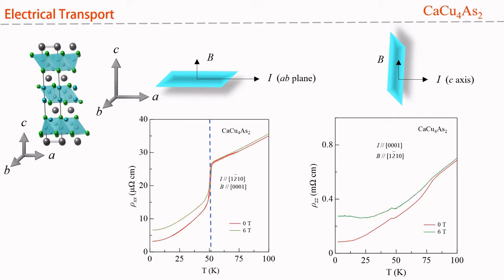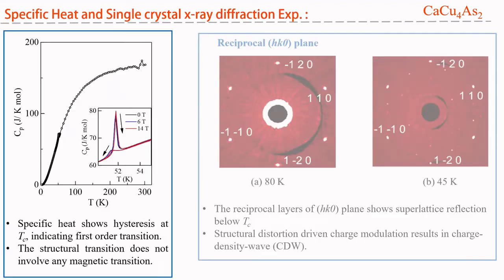In presence of magnetic field, the resistivity increases slightly for both, but if we increase the field value more, we find C direction resistivity increases rapidly, indicating poor conducting nature, whereas no such increment is found for along AB plane resistivity. The transition at 51 K is due to charge density wave, which is further confirmed by heat capacity and single crystal X-ray diffraction experiment.